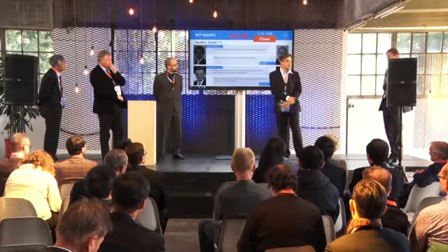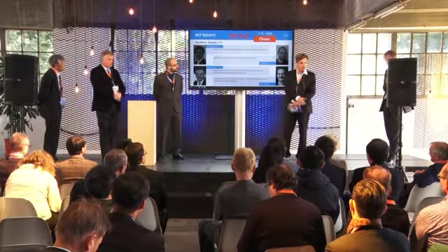As Richard said, white etching layer appears on most railway systems, and you can find white etching layers on most rails, but not on all rails. You find squats or studs or new squats. And as you saw in our test rig results, white etching layers can lead to cracks, outbreaks, cracking the base material, and so on. But that doesn't mean that such cracks or outbreaks can develop into a squat or a stud or a new squat. It can just be the initiation point for the development of a squat.